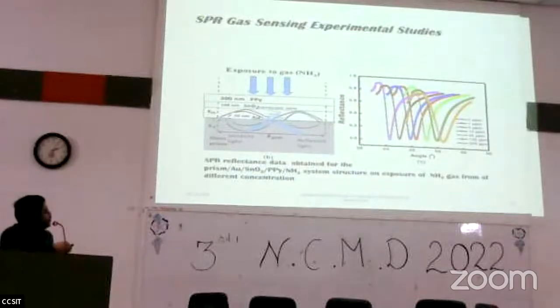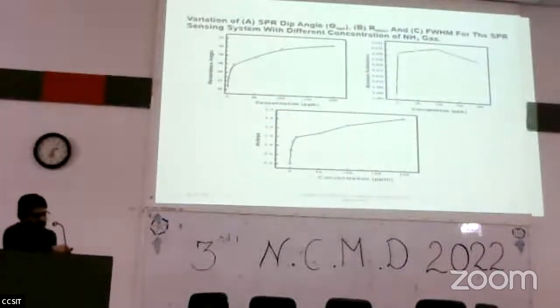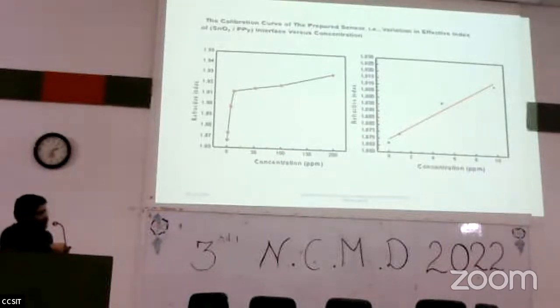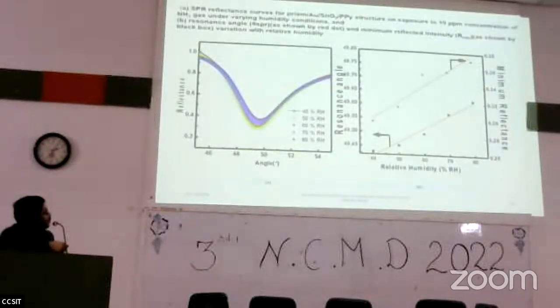So this is our experimental studies. We take the optimized thickness of polypyrrole as 300 nanometer and 100 nanometer tin oxide, then observe the SPR reflectance. We again vary the concentration from 0 to 200 ppm. These are the three parameters: minimum reflectance, resonance angle, and full width at half maximum for this sensor. Again, refractive index variation with concentration. So this is the humidity study of this sensor. It was done at 42 to 80 RH. There is a shift in the minimum reflectance and resonance.